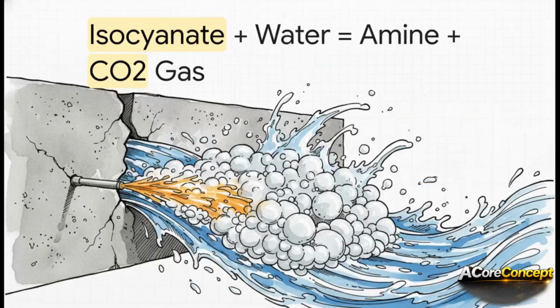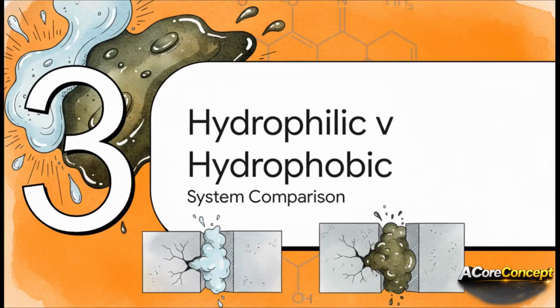Now this right here, this chemical equation, is exactly why PU is so unbelievably effective against active water ingress. The reaction literally uses the leaking water to its own advantage. When the isocyanate hits that water, it reacts to form an amine and carbon dioxide gas. And that CO2, it acts as a blowing agent. It causes the resin to rapidly expand and forcefully fill the void, creating this watertight pore structure that completely stops gushing, high-pressure water leaks dead in their tracks. It's brilliant.